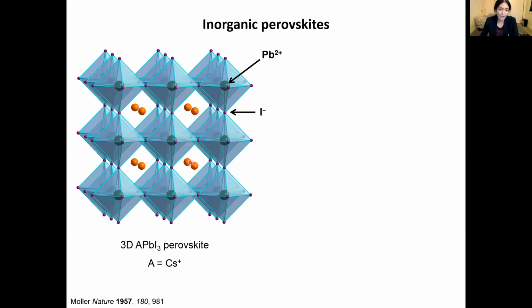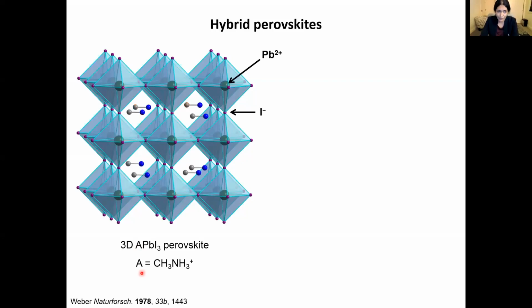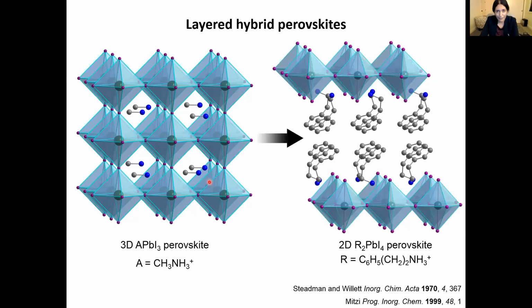When this positive ion or cation is an inorganic ion like cesium, potassium, or rubidium, this would be your standard inorganic halide perovskite. But you can also imagine stuffing small organic cations into these cavities as well. For example, methylammonium will fit this cavity. And in that case, these materials are called organic-inorganic perovskites or hybrid perovskites. If I were to try and stuff in an organic molecule that's slightly too large for this cavity, we can still form a perovskite, but often we'll find a lower dimensional analog, like the 2-dimensional perovskites shown here.